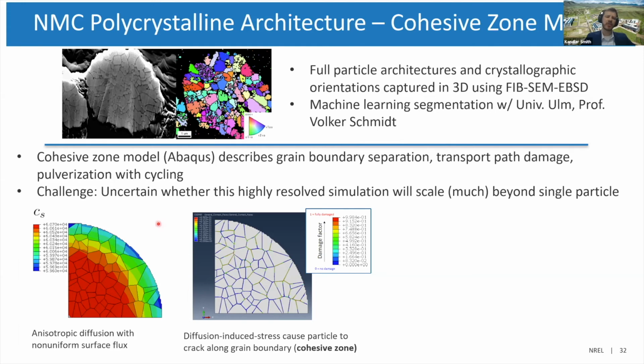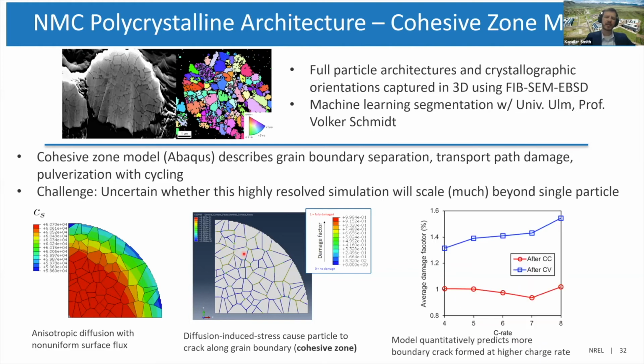And so we have presently built this up in 2D. We've got it partially into 3D for smaller geometries, and can track a damage factor which describes the grain-grain separation and also the transport path damage. So this particular model is just some early results from this after constant current. We don't see much change in the damage factor at different C rates. That's because as you go to higher and higher C rates, you cut off sooner.